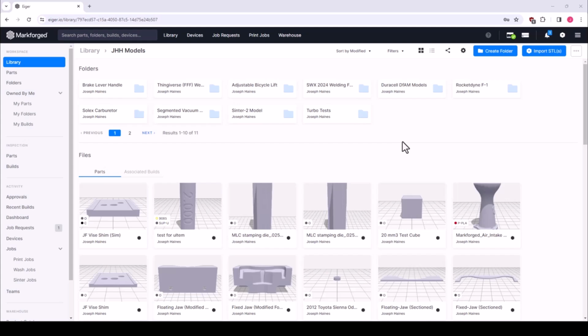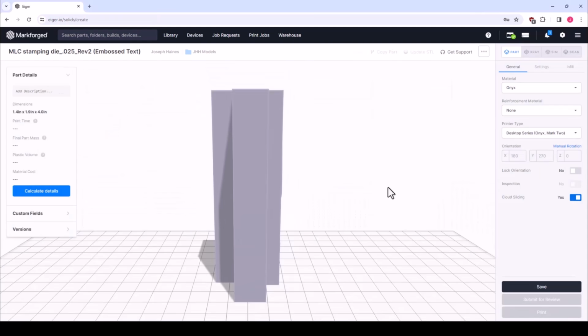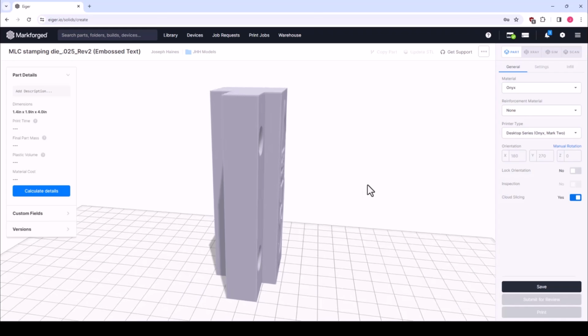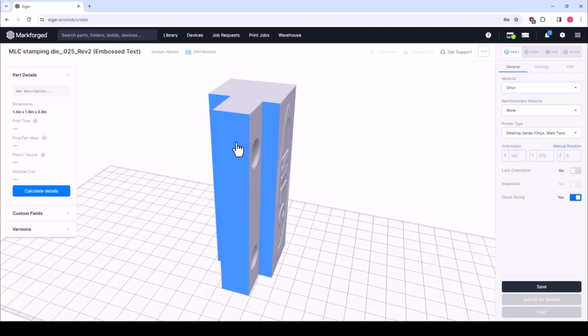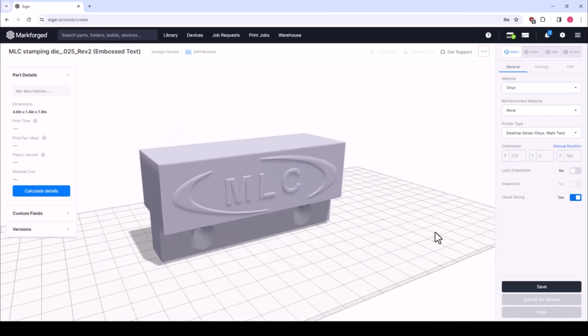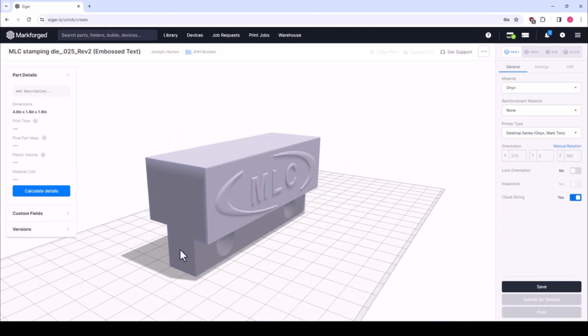In Eiger, Markforged's slicing software, I imported the STL files. These parts are a really interesting study on part orientation. If I were to orient this part on this face, with the layer lines building up like so, I actually run the risk of layer delamination. The compressive force on this face of the die could actually cause shearing between the layer lines of the part. This, fortunately, can easily be avoided by adjusting your print orientation.